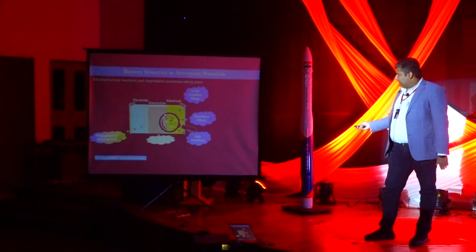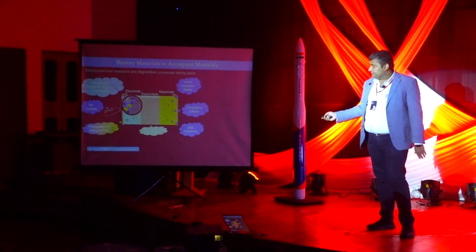And then what happened is that it's not sufficient, because the entire field requires much more depth. So barely looking at what is happening during the process isn't sufficient. There were a lot of electrochemical reactions and degradation processes taking place during the whole process, for which we needed to identify the local oxidation states, correlative effects which might result because of reaction with the electron beam, and side reactions which might be caused by the movement of ions, or propagation of the charging front. Of course, the influence of the interfaces, the grain boundaries also exist.